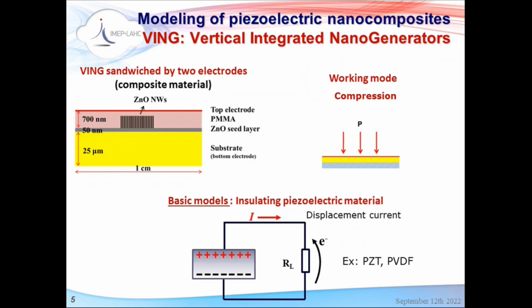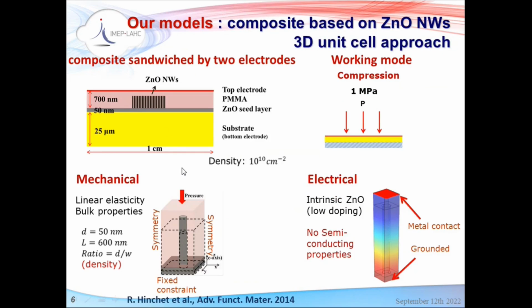How can you simulate this kind of materials? First thing that you can do is start simple and consider that the materials are dielectric. This is the case of most piezoelectric materials, for instance, PZT or PVDF. So basically, when you deform them, you obtain the polarization, as I explained before, and you can use this potential either in sensors or energy harvesting, for instance. You can connect a resistance here to the piezoelectric device, and you can make current flow. All right. So that's how we started, considering the nanowires as dielectric, although they're not. But let us see what happens.